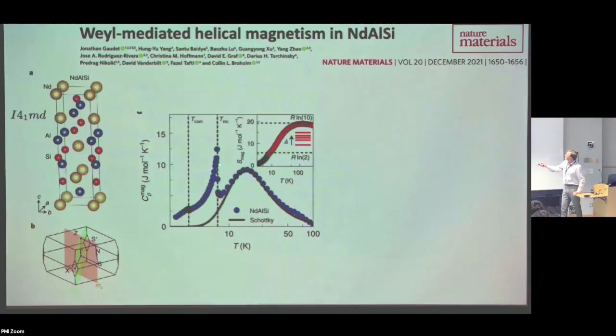And then there are actually 2 phase transitions. First, a transition into an incommensurate state, and then at a lower temperature, a transition to a commensurate state. That's a very normal scenario for rare earth metals like this. It doesn't have to be a Weyl material for that to happen, but there are some aspects of the incommensurate structure that we think can be associated with the Weyl structure in the electronic band structure.